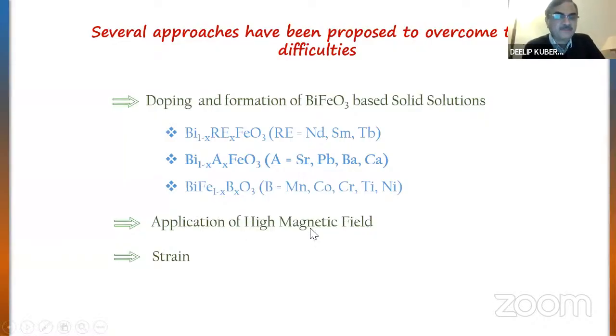Then, application of high magnetic field. Application of high magnetic field also takes care of the inhomogeneous spin structure, and therefore we can make this material suitable for the applied purpose. And lastly, but not the least, is the development of strain, or modification of the strain in the material. And this strain can be modified only if you can grow this material in the form of thin films, that is, two-dimensional materials. Just now we saw a lot of interesting results on the films. So films are very important for the device, for any type of application. Your normal powder or bulk materials are of no use. So we have to make very high quality films, and then if you can modify the strain in the material, you can overcome some of the difficulties of using BiFeO3.